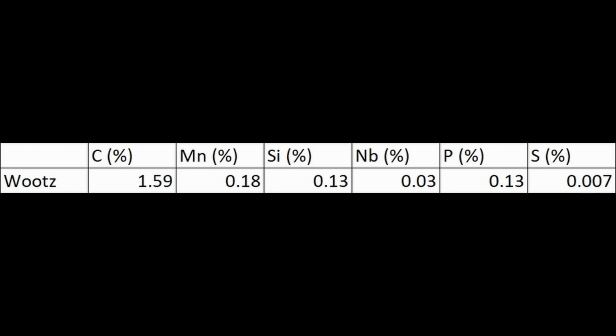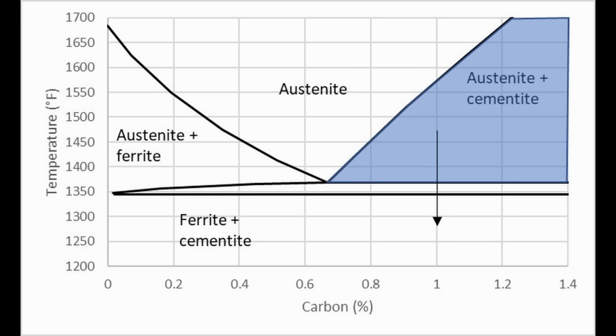So the more thermal cycles you get, the more banded the microstructure becomes, until you get carbide bands that lead to the pattern. I measured the composition of Spencer's Wootz that he sent me with optical emission spectroscopy and also LECO combustion. OES is a very good technique, though its carbon and sulfur measurement is not as good as LECO because they are very light elements. The combustion method is very good at measuring the light elements. So the carbon turned out really well, 1.59%. That's right around the average of ancient blades, which is approximately 1.5% carbon. As we mentioned, that high carbon is necessary to get a wide two-phase region so that overheating during the thermal cycling is not as likely. The more carbon, the higher the temperature at which those carbides survive before they dissolve.